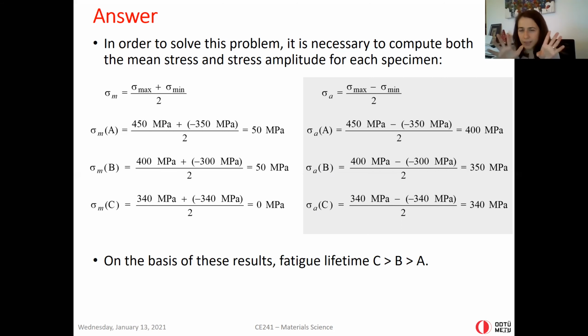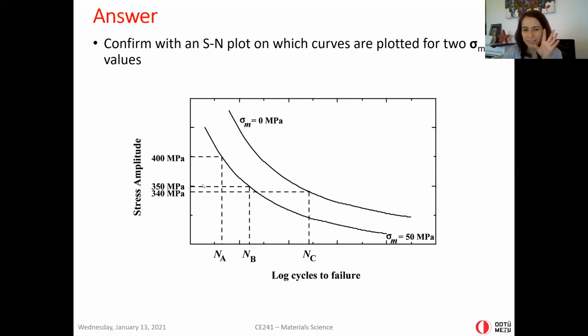So just looking at these, I can clearly and easily say C is larger than B, larger than A. Okay, let's go through them in a graph. So here it is. We have C and we have A and B. The mean stress for C sample is 0. So it has a lower mean stress, and that means it can have a longer lifetime. For specimens A and B, you have a mean stress of 50 megapascal, which means they will for sure have a shorter lifetime. So we know C wins. Plus also the stress amplitude calculated for C is 340 megapascal, which is also lower. So for sure, C will have a longer lifetime.